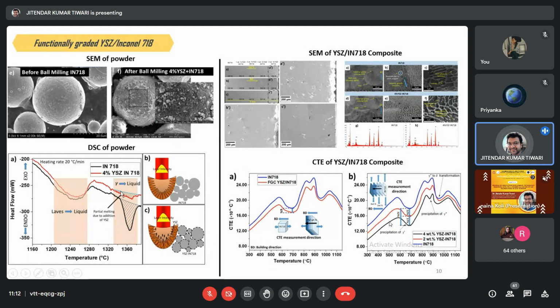You can see here the red graph is representing the 4% yttria stabilized zirconia in Inconel 718 mixture, and this black curve is representing pure Inconel 718 powder. What is happening here is that you are getting a deeper peak. It is an endothermic peak, which means it is absorbing energy. It is taking too much heat, and it is actually melting properly. That's what it is representing.